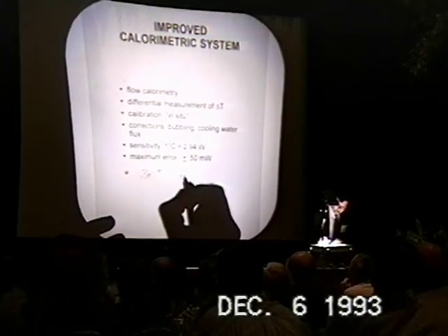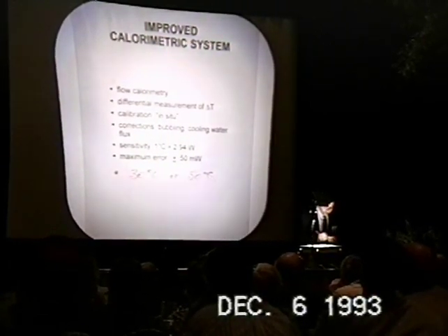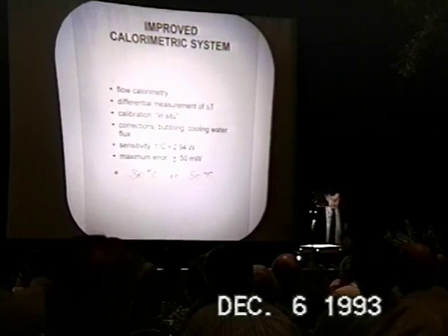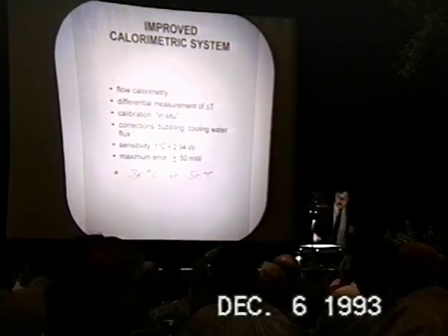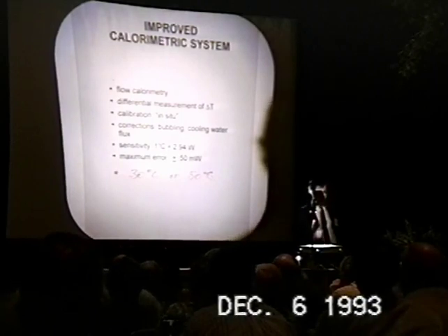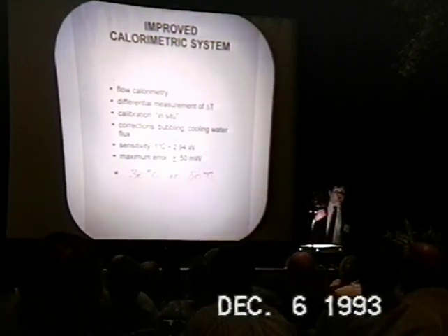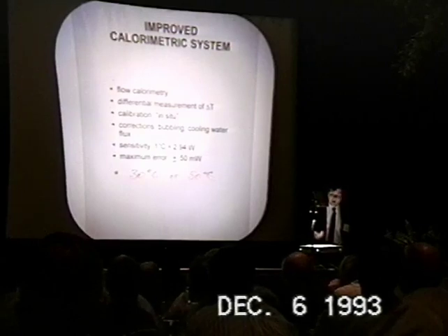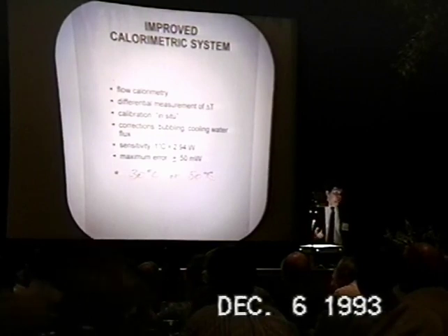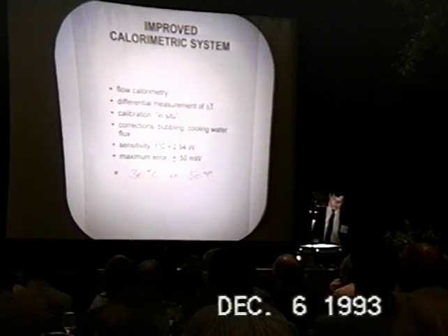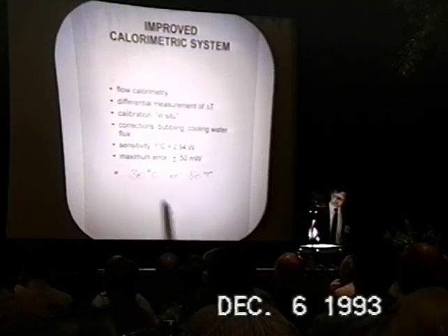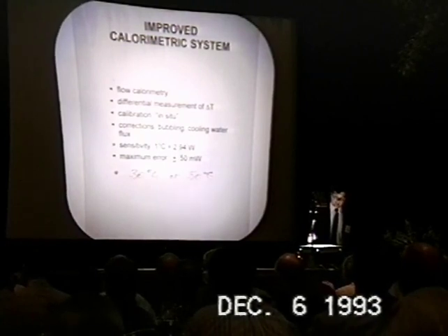Our system can work at 30 degrees or 50 degrees Celsius. We can set up our box temperature at these two temperatures. We are quite interested in doing measurement of the loading ratio and heat production at high temperature without going up to very, very high current. So with this system we can see the dependence on the temperature.